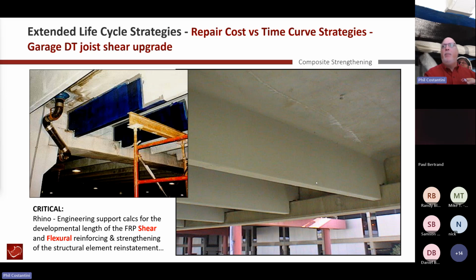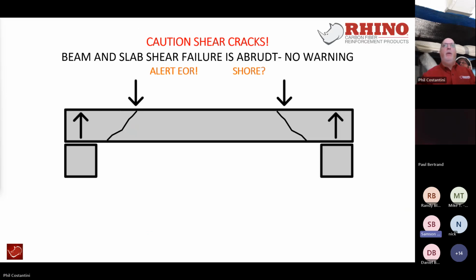And again, just a typical cementitious coating was applied here to mimic concrete, and it also gave it, for whatever reason, they wanted an additional 4-hour rating. So we had a cementitious waterproof coating put on there that was UV protecting. But most importantly, the beam was put back into service, and this area was put back into service so that they didn't lose any critical time or parking stalls. And you can see we basically worked within a confined area of what we needed to do the repairs and get the developmental length that was required of us to get that double T back into shear upgrade.